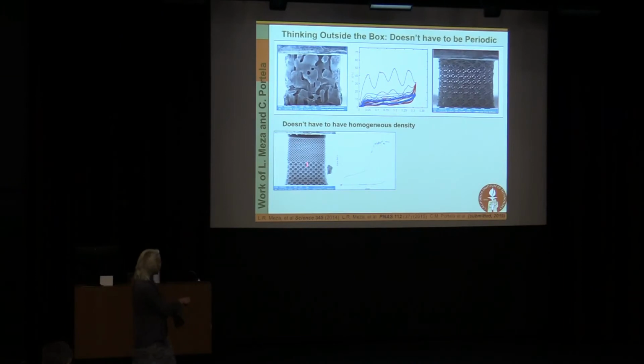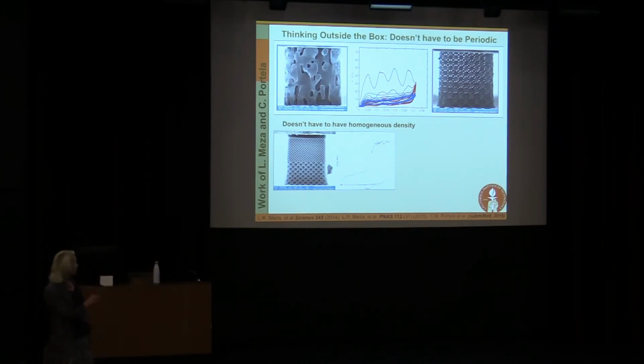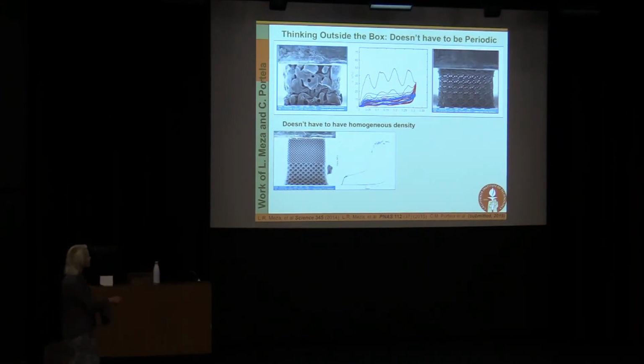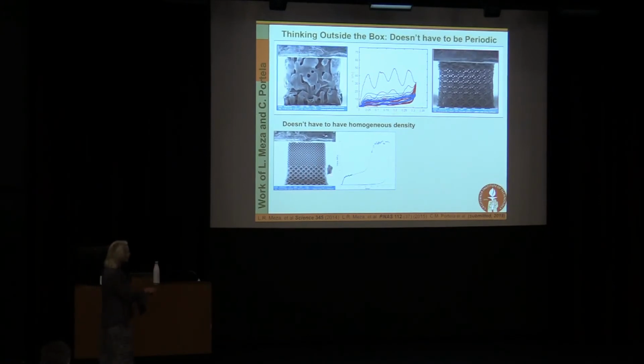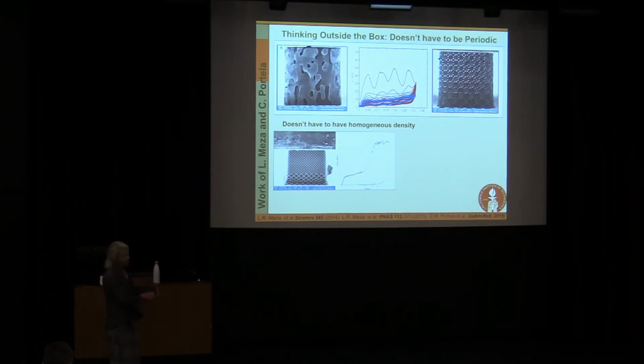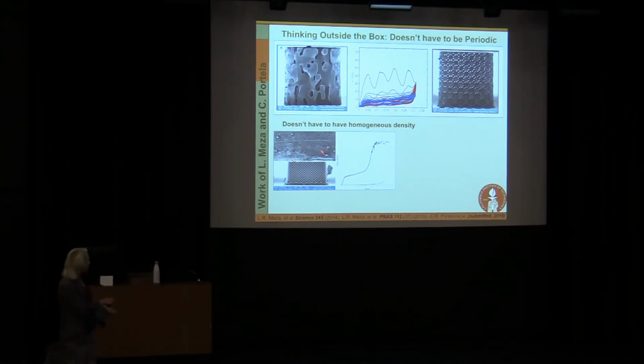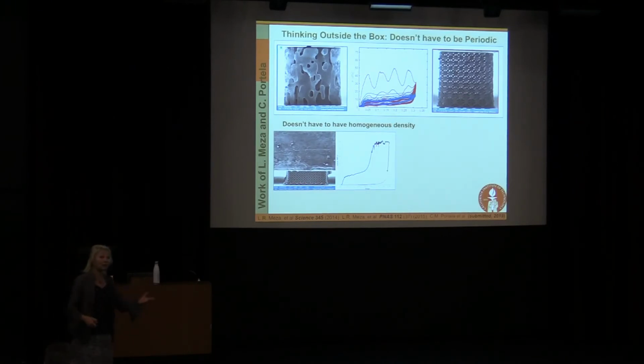You can see that the density doesn't have to be homogeneous. In fact, we can prescribe different density regimes. So watch what happens when we compress this one. So there, of course, this is the lighter, this is the less dense region, and so that's the first region that's being compressed. And then this part doesn't even know that it's being subjected to any kind of mechanical loading. And then only after we've fully densified and compressed the bottom part, this becomes the load-bearing element. And so now you can prescribe different architecture and different trajectories of how and where your material is going to deform.